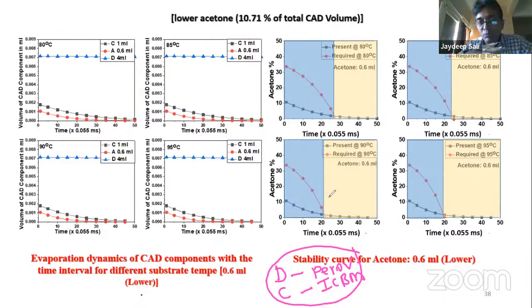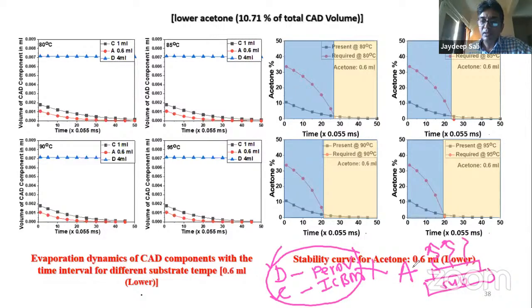So when this microemulsion is put on a substrate and the substrate is heated, naturally the DMSO as well as cyclohexane start evaporating. Not only these two solvents, it has an additional acetone also. Suppose this is a substrate, and on this we deposited a thin liquid film of this microemulsion. So evaporation of the solvents will start, and the evaporation rate of DMSO, the evaporation rate of cyclohexane, evaporation rate of acetone, all are different.